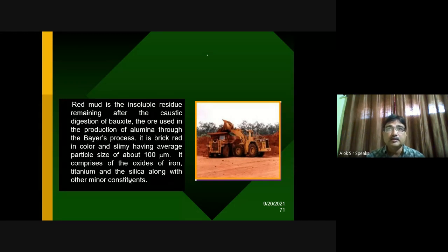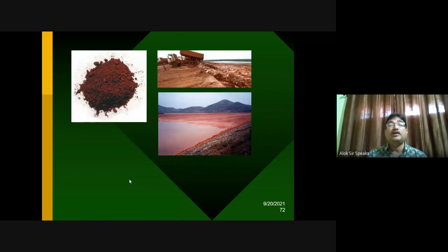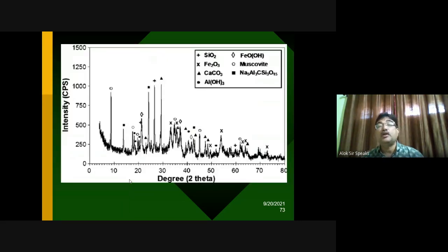Their health is getting affected, and it is a known pollutant. But if it can be used for some value-added applications like composite making or coating making, then maybe a part of that can be properly utilized to make some value-added product. Keeping this in mind, we tried this red mud coating, and we did an X-ray diffraction test of the red mud. We found different constituents like silica, iron oxide, calcium carbonate, and a little bit of aluminum oxide as well.